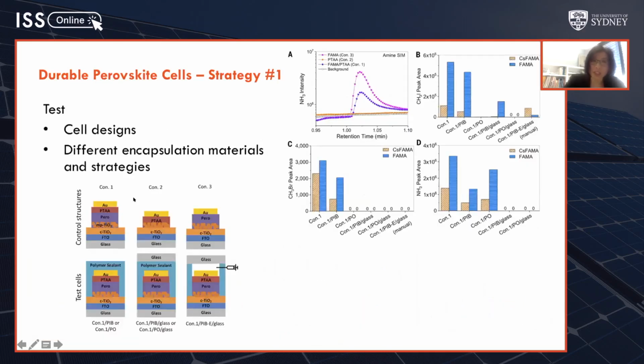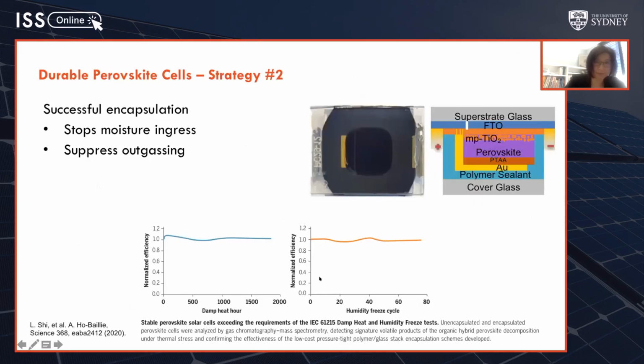We also use the GCMS to test the different cell designs to see which layer in the cell is outgassing, if they do, and also the different encapsulation materials. For example, we look at two types of polymer, a polyolefin one and polyisobutylene. They're both used in double glazing technology. And we also look at whether it is a blanket-based or edge seal-based method, which one works better. So finally, we found that the blanket approach is the best.